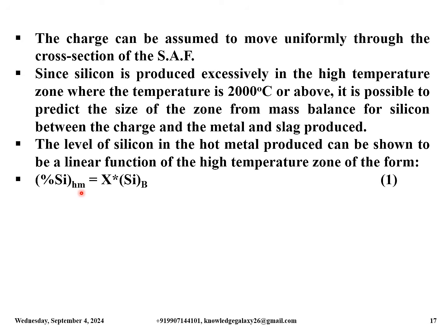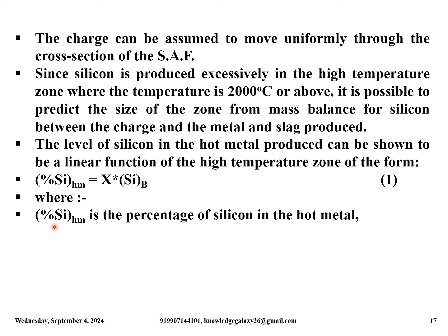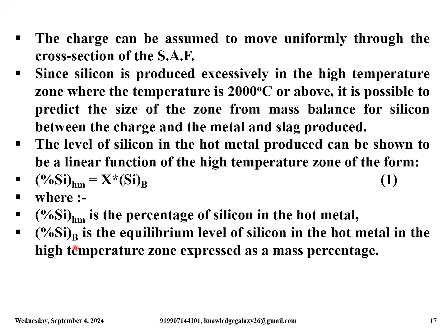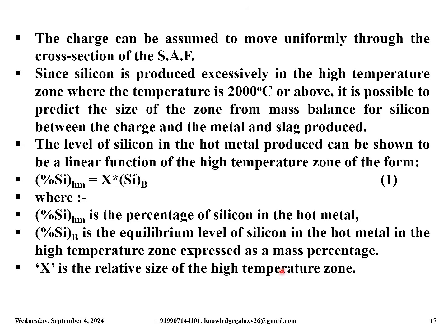Percentage silicon hot metal is equal to X into silicon B. This is equation number 1, where percentage silicon HM is the percentage of silicon in the hot metal. Percentage silicon B is the equilibrium level of silicon in the hot metal in the high temperature zone, expressed as a mass percentage. X is the relative size of the high temperature zone.